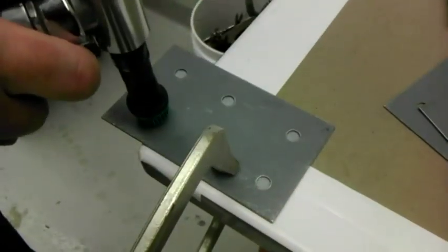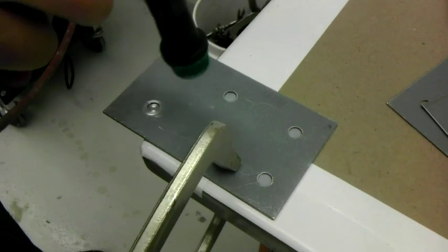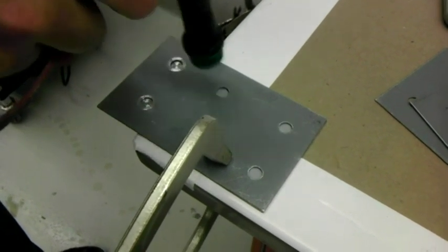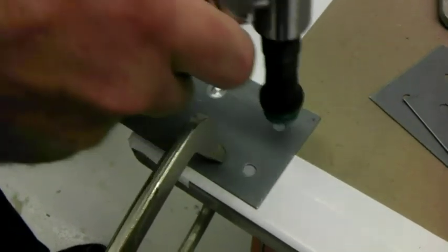Well, speaking of roll-out grinding discs, let's talk about what's the proper way to use weld-through primer, Shawn? Well, if you need to use weld-through primer, and if it's recommended, you want to clean it out of the weld zone. So when you overlap your top panel and you can see the weld-through primer in the bottom of the punched hole, that has to come out of there. That's got to be cleaned out.